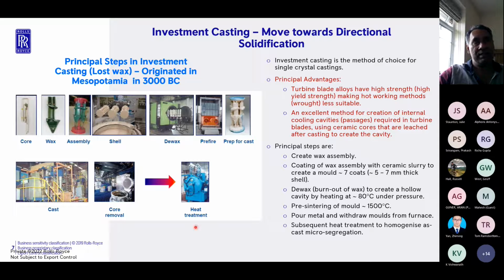Now this blade is in the cast condition, and as you would know, one of the major drawbacks of casting is you end up with segregation, simply because the solubility limits of an element in the liquid and the solid are not the same. Some elements segregate to the liquid, some to the solid, and in the nickel-based alloys that we use, elements like rhenium, tantalum, etc., chromium, they've got very strong segregation tendency. So you've got a lot of micro segregation that exists across a casting.